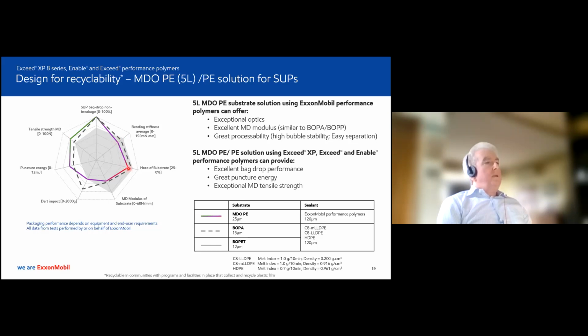In terms of the optics, it's also pretty good. And again, if you're running an unoriented PE substrate, then that would be a lot more defensive than that. If we move across to the stiffness factor, this is particularly pleasing because now we've got stiffness pretty much the same as the BOPA solution, but not obviously as good as the BOPET solution. The dart is obviously a very strong attribute of the nylon type of structure, but we are at least as good as the BOPET.